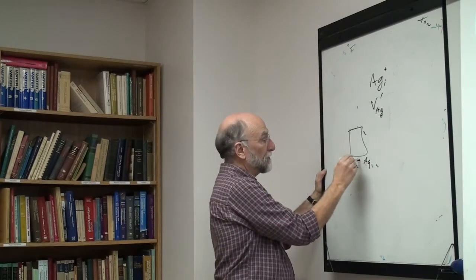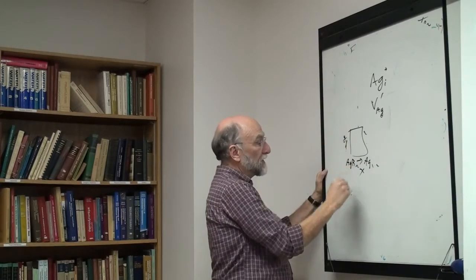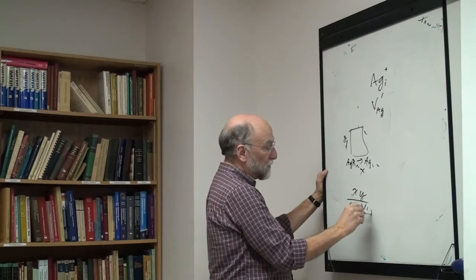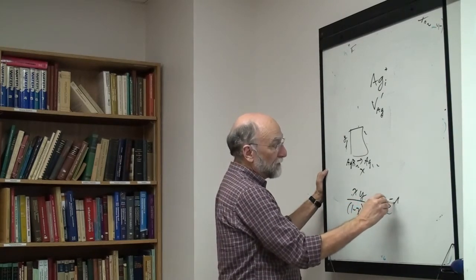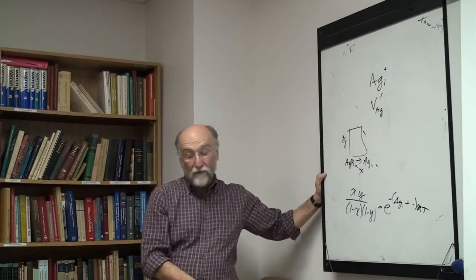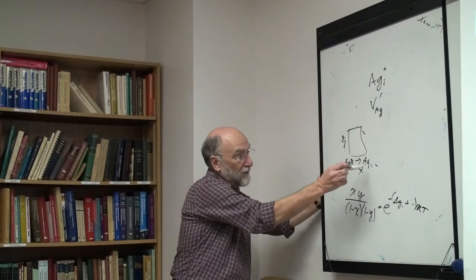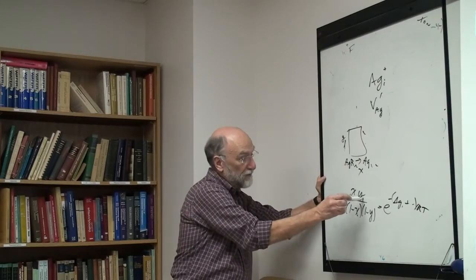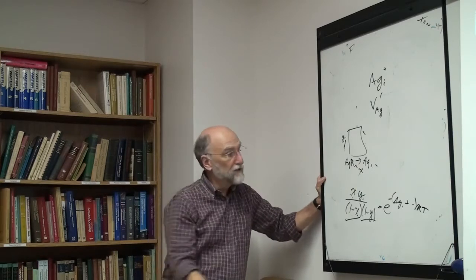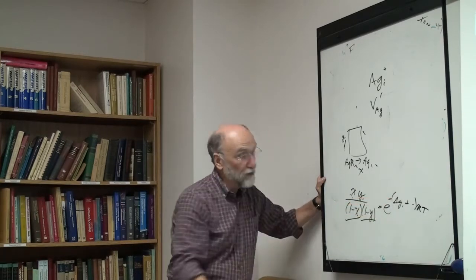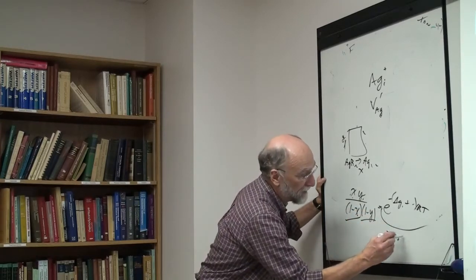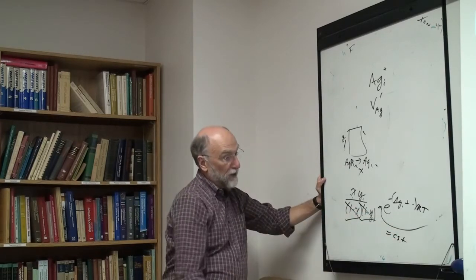Here you end up with the concentrations of the two defects, and you always end up with xy over (1 minus x)(1 minus y) equal to the exponent of something, minus delta G1. You always end up with something very close to this. The product of this defect times the concentration of this defect, divided by the concentrations of the defect-free sites, is equal to the exponent of some sort of an energy term for forming the defects. This is approximately constant. The denominators here are approximately 1.